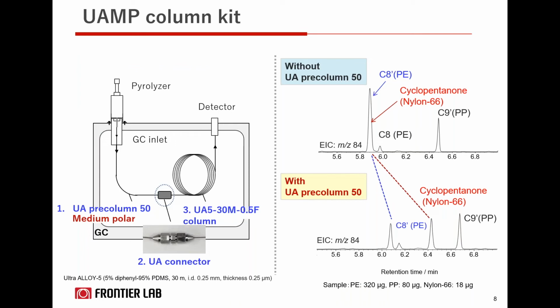So now moving on to the other parts of the system configuration, the UAMP column kit, which is Ultra ALLOY. UA stands for Ultra ALLOY. The microplastic column kit consists of a separation column, a UA5, that's 5% diphenyl, 95% PDMS, a pre-column that we call UA pre-column 50, which has a medium polarity, and also a UA connector. This kit, including the column and the pre-column, really improves the accuracy of qualitative and quantitative analysis of plastic mixture samples using F-Search MP 2.0. Also, this product reduces the contamination of the separation column, thus reducing the replacement frequency of your column.